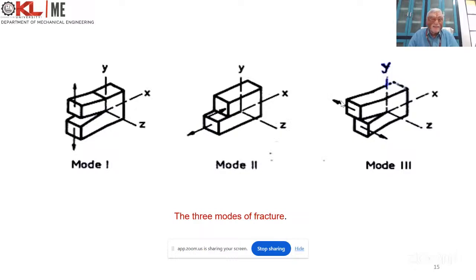So there are three modes of failure. One is the opening mode. You apply load perpendicular to the crack surface, the crack will try to open, and it will grow and fail. Then the sliding mode, shear type, and the tearing mode, the third mode. Out of these, in mode 1 the toughness is low, so it governs the design. The other modes are still higher. If you design based on mode 1, failure of the structure by other modes will be rare. So with that, designers adopt mode 1 fracture toughness.